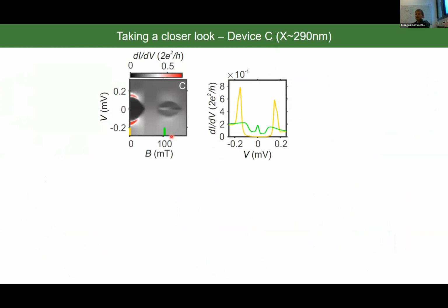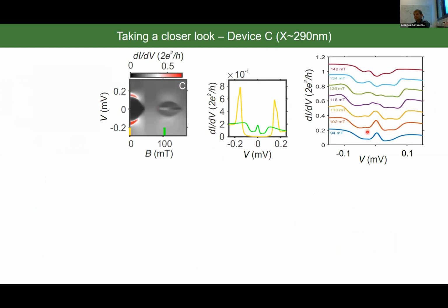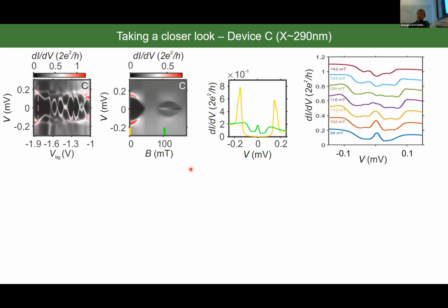You see in the first lobe a zero bias peak, which actually splits as you crank up the magnetic field, as you can see here in the measurement of the differential conductance versus the magnetic field. You start with a beautiful zero bias peak, which splits as you crank up the magnetic field. Let's take a look at how that device looks if we start changing the backgate voltage. What I show you here is a zero magnetic field measurement, where we sweep the bias versus the backgate voltage. The dashed pink line is the position for which this plot has been taken. So obviously, this device also has Andreev bound states.